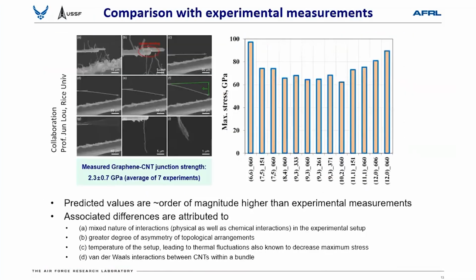But more practical option. Oh, one more thing I want to say. Those calculations are a very idealistic case, meaning very pristine CNT, but in reality that doesn't happen. When we compare our prediction with the measurement, this is the work we have done in collaboration with Professor Jun Lou from Rice University. He did the strength measurement with AFM. The measured strength is quite low, 2 orders of magnitude, I would say, lower than what we are predicting.